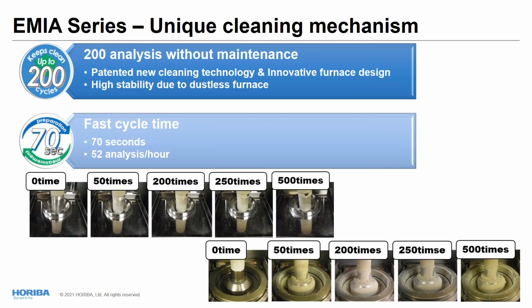But the main advantage is that this new mechanism is very efficient and it can provide up to 200 cycles, potentially up to 500 cycles on some samples without any maintenance needed, because it provides literally dustless operation, as you can see here from the beginning of the first sample to the 500 analysis. You can see there is almost no dust on the system. You need to compare that to a standard system where you see at the beginning it is clean and really quickly you accumulate dust around the crucible and on the crucible stand, requiring typically maintenance after 50 to 100 cycles.